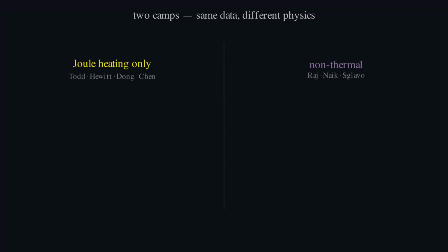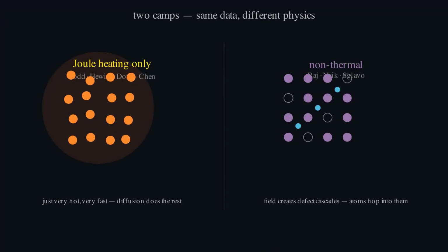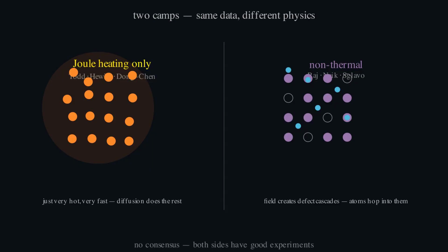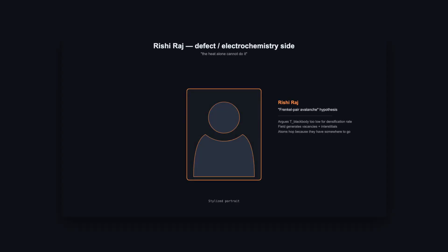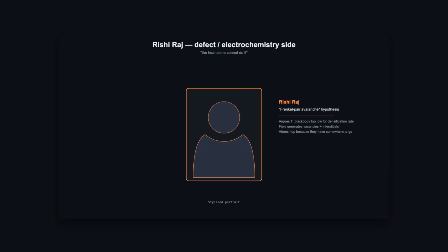On the other side, Rishi Raj himself, working with Hasan Naik, Sglavo, and others. Raj's argument starts with measurements, not theory. He points out that if you estimate the temperature from the black body glow of the sample, and you compare it to the densification rate, the diffusion you would need at that temperature is not enough. You would need to be hotter than the sample physically can be. Something else is moving atoms.